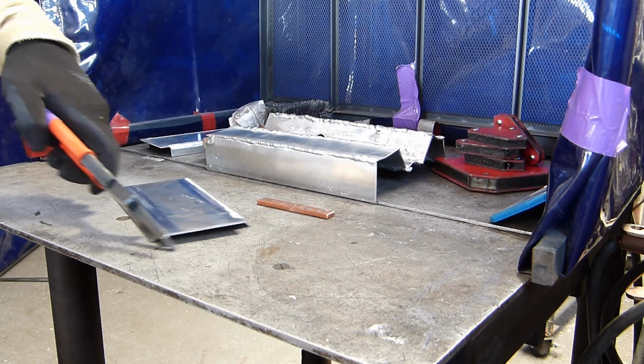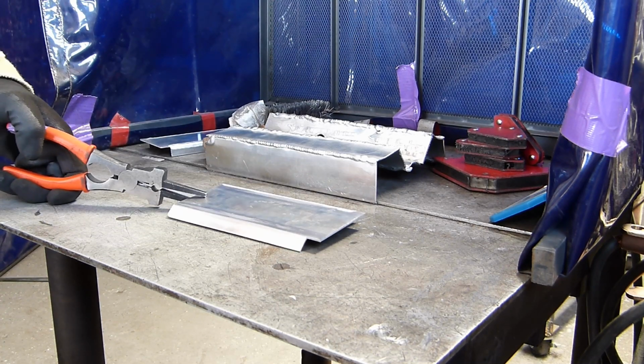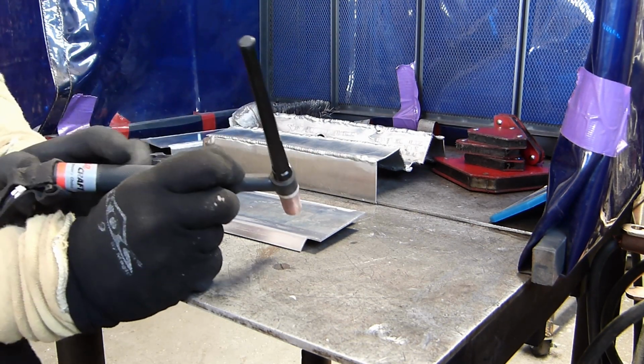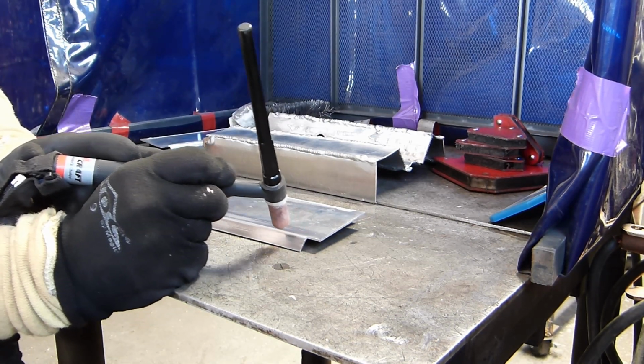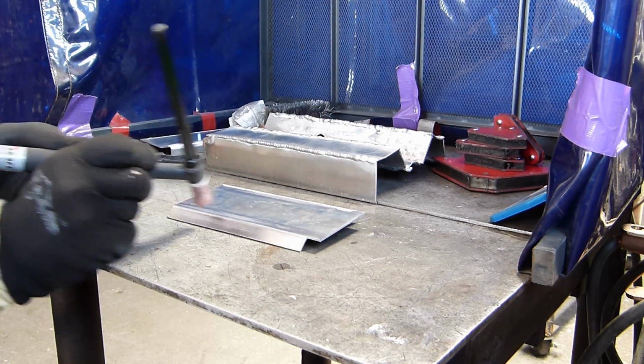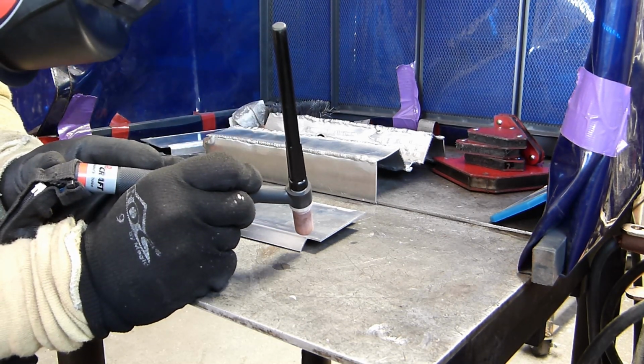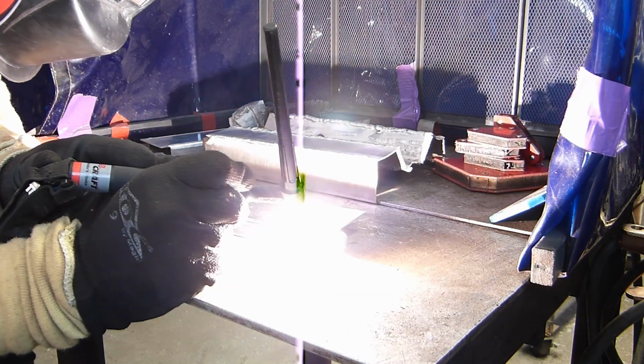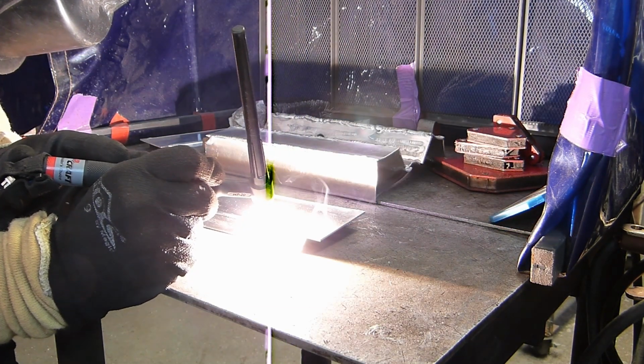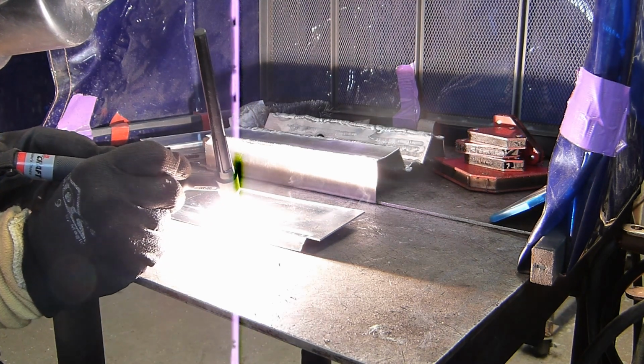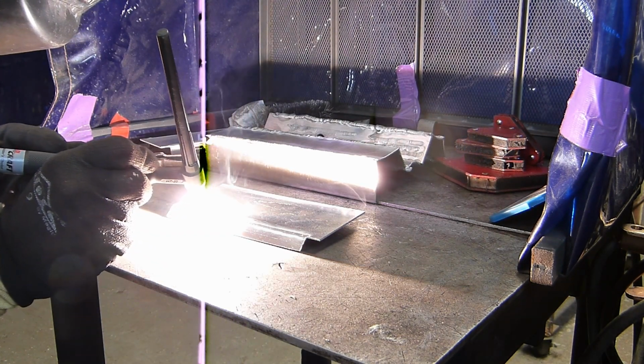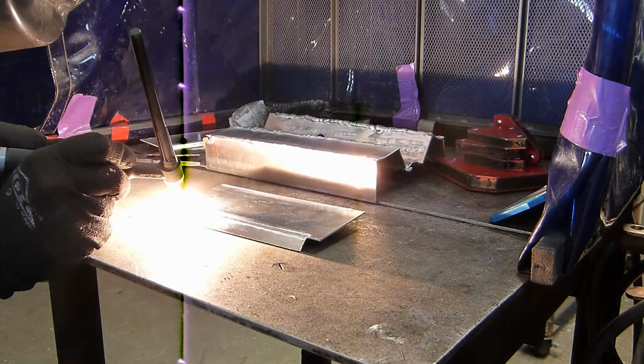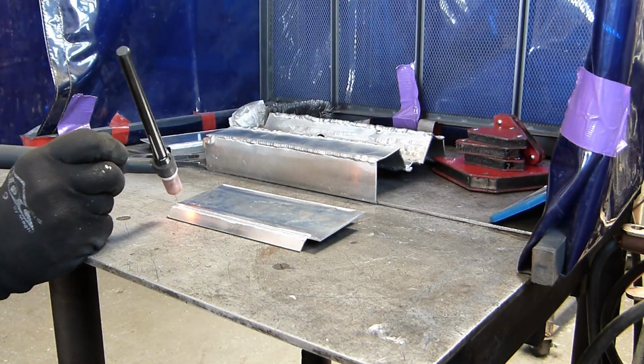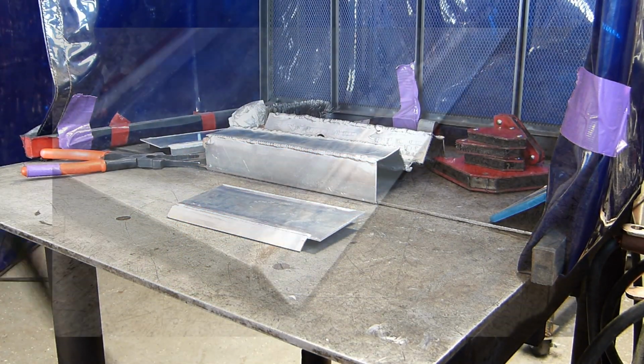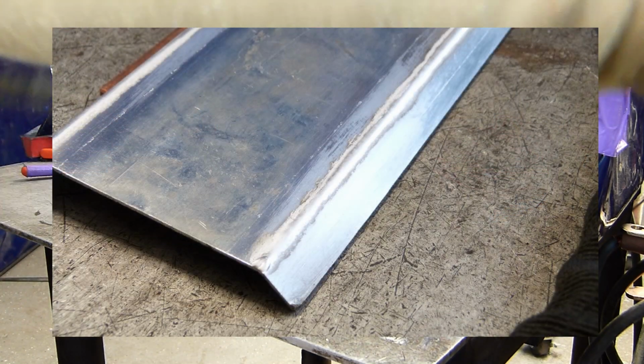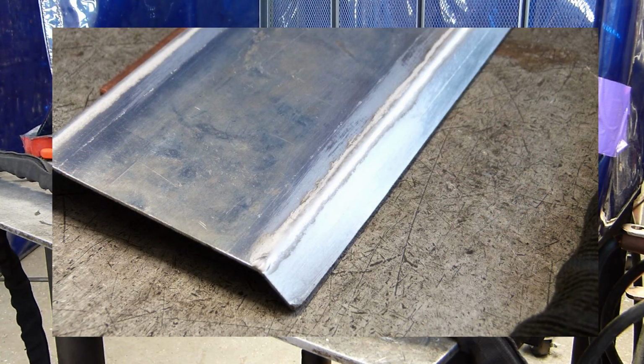And in addition to that, I'm using the heat affected zone to my advantage. So I am creating a more ductile material at that corner by going above the transition temperature, as well as filling in those cracks. So then I can complete the bend to 90 degrees with absolutely no problem. There's no problem. I could probably go farther, because again I covered up those cracks, and by going 45 degrees initially, I can reduce the stress on the final bend.